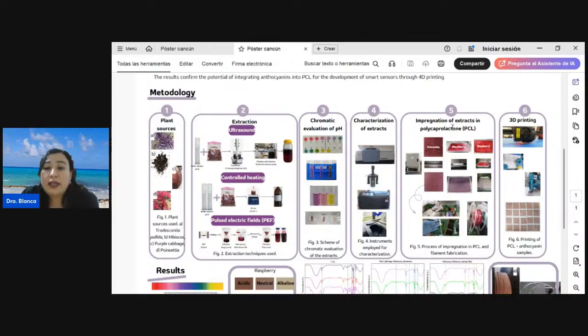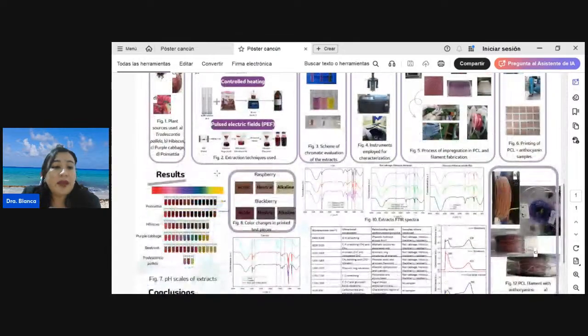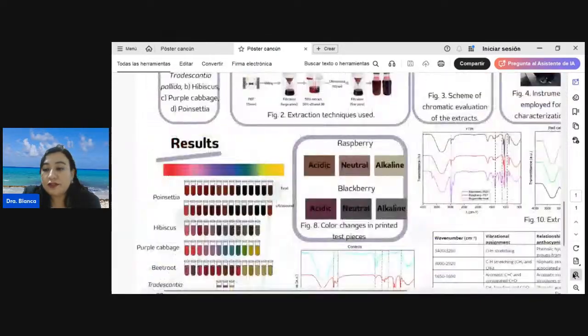Finally, we impregnate the extracts in polycaprolactone, PCL, and we made a filament for printing in the 3D printer, a Creality printer, and we use it in a pen. Finally, we obtained the PCL and anthocyanin samples. The material was colorful, and for the results,